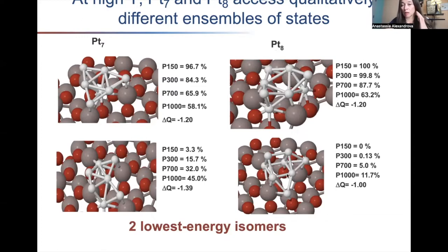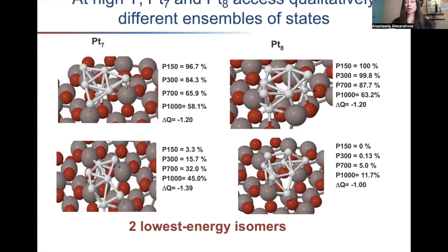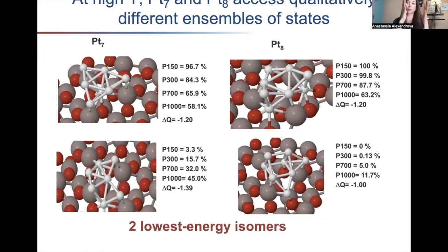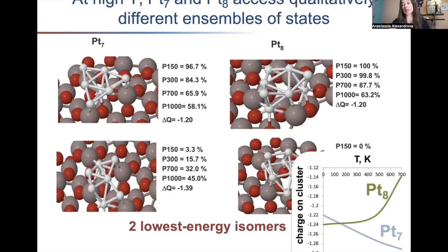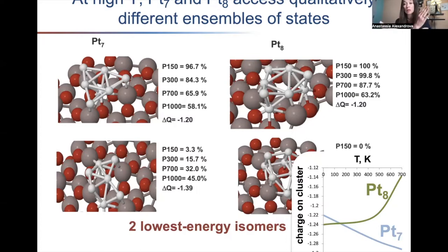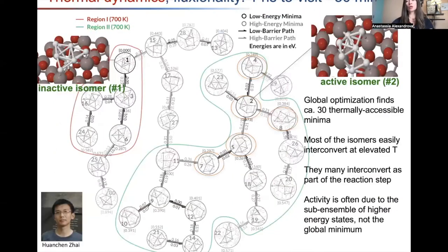That flatter family of isomers for Pt7 is quite populated at 700 K. For Pt8 though, we have qualitatively different behavior: the first accessible isomer above the global minimum is less populated than LM1 for Pt7, and is more globular, featuring more Pt-Pt bonds and fewer Pt-support bonds — taking fewer electrons from the support. If you compute the ensemble-average charge — weighted by Boltzmann probability — Pt7 and Pt8 diverge as a function of temperature, meaning ensemble size.